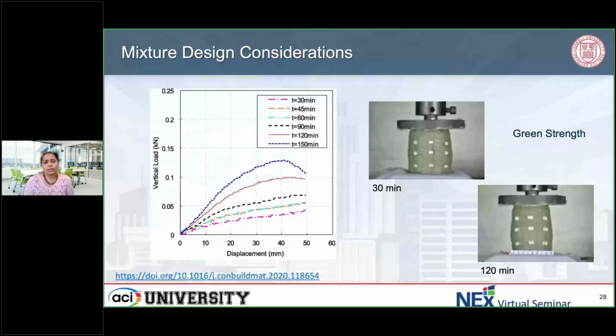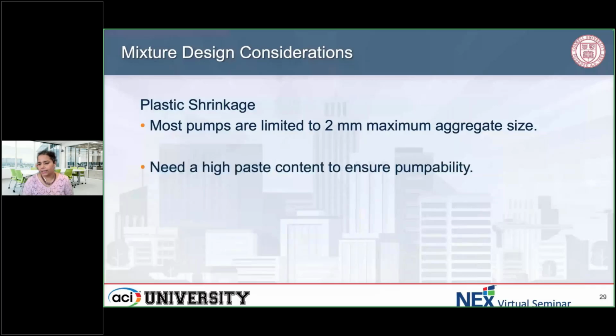Another material design consideration that you have to keep in mind for 3D printing is plastic shrinkage. Like I said, most pumps right now are limited to 2 millimeter maximum aggregate size, and they also need a high paste content to ensure that the material is pumpable.